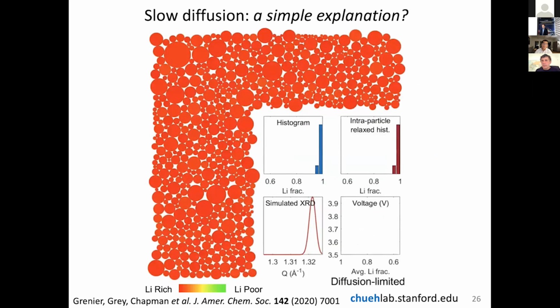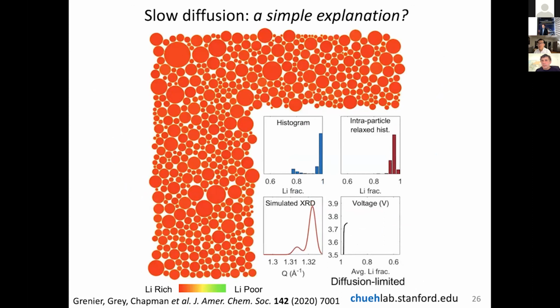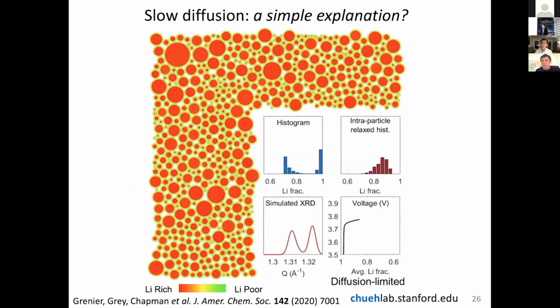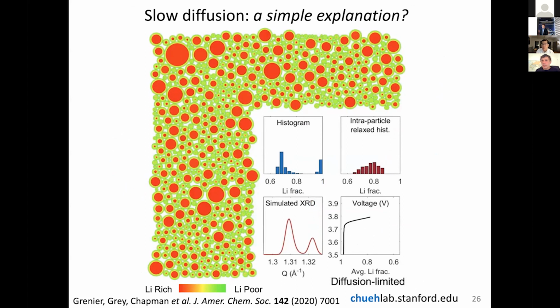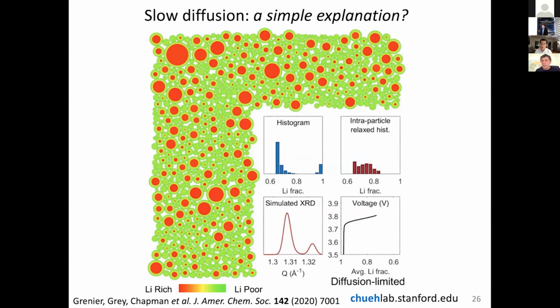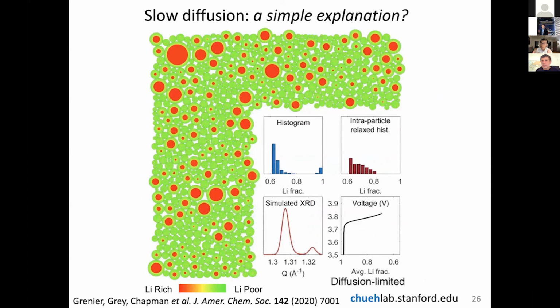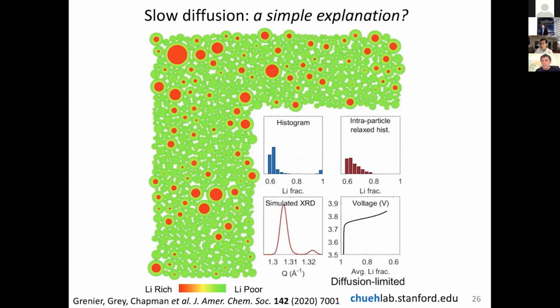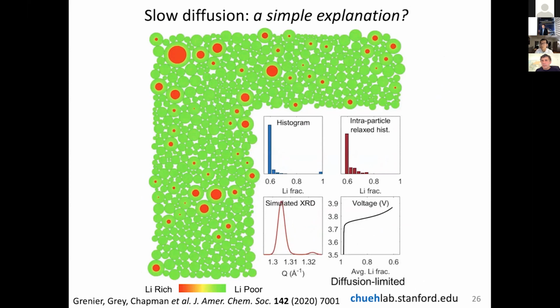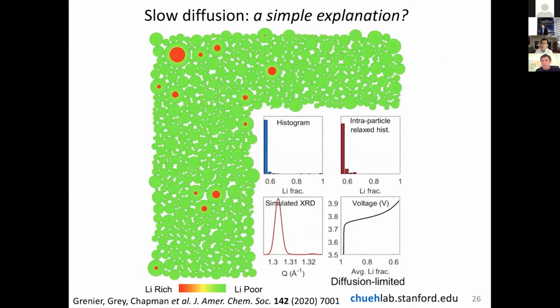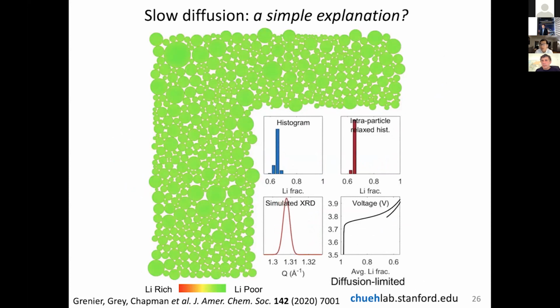So when we first saw this phenomenon, we thought, oh, this must be just a diffusion front, because the diffusion front can perfectly explain the observation. You have basically what I'm showing in the animation here. You have very slow diffusion in the particle, so you form a moving front, and when you do X-ray diffraction, the two compositional ranges of what looks like phase separation is nothing more than diffusion. So indeed, the X-ray diffraction results can be explained by slow diffusion.